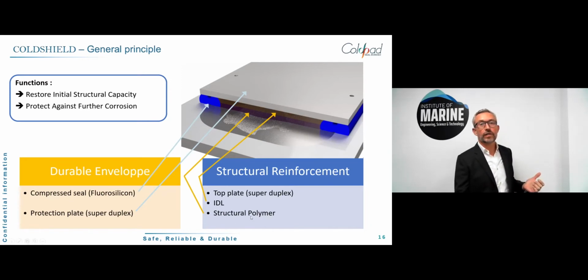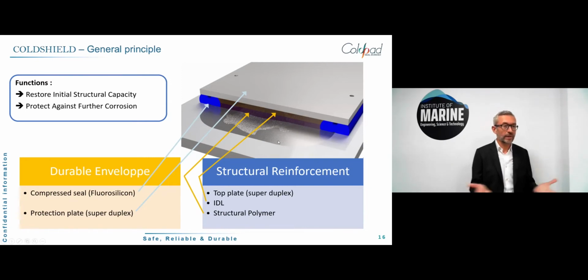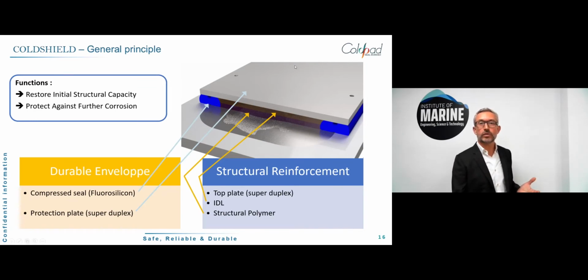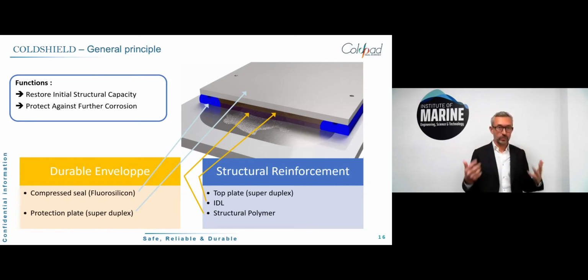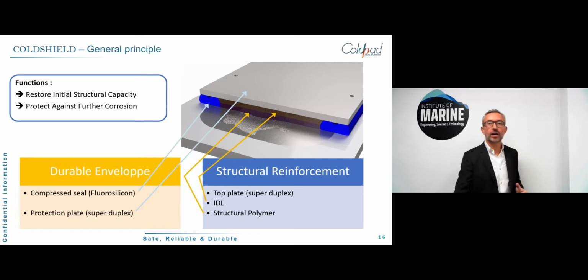What you could notice on that, the steel substrate, the base metal is naked here, meaning that we have done the surface preparation before in order to make sure that we have good adhesion between the structural polymer, epoxy resin, and the reinforcement. So this is the structural reinforcement that you can see, which is made of a plate. It's the steel plate, the super duplex here, will be the reinforcement. And there is also an intermediate layer that I will explain what its function is. And of course, you have to inject the epoxy, which is in dark color in that. So this is the structural reinforcement.